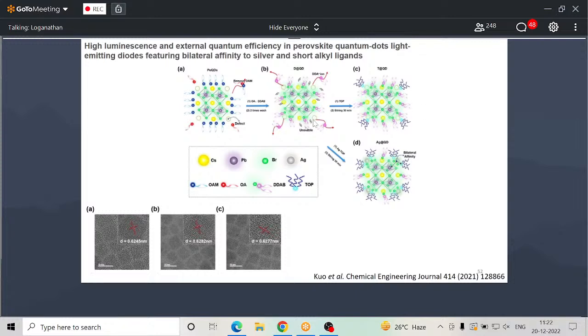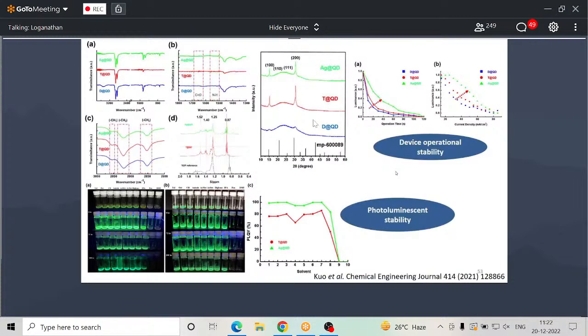In this case, we compare the conventional system and the DDAB system. Here you can see this ligand is the conventional one, OA, and DDAB is this one, which is sterically hindered, and TOP is more sterically hindered. So which will be giving very good stability and structural aspects. Here we can see the XRD crystallinity peaks here among Ag, if we put some silver, which is going to promote our stability as well. And here we can see the PLQY. PLQY is nothing but photoluminescence quantum yield. If the PLQY values are quite high, it means the efficiency of your LEDs will be good. And we also check the stability towards different solvents, because we are going to process our perovskites in different solvents, right?